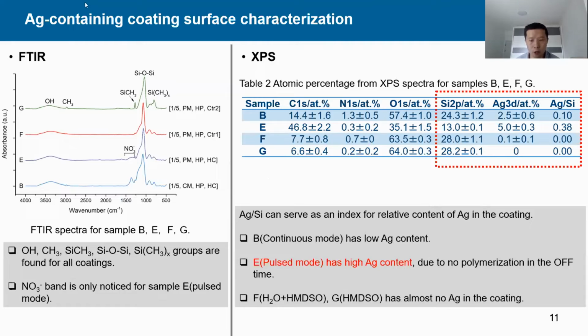XPS gives more information on coating chemistry. In table 2, we can focus on the silicon and silver. The ratio of silver over silicon can serve as an index for relative content of silver in the coating, as we notice that the silicon is rather uniformly distributed on the surface according to EDX results. In the pulsed mode, sample E shows a higher silver content than sample B in the continuous mode due to no polymerization in the off time. In samples F and G, almost no silver is found in the coating.